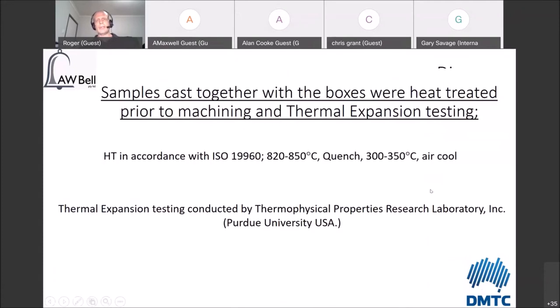So samples that were cast together with the boxes that I showed you before were heat treated prior to machining and thermal expansion testing. The heat treatment was done in accordance with the ISO standard. The specification here is just straight out of the ISO standard. We chose parameters inside of that, and it's pretty straightforward what you need to do. There's nothing special about it. And then thermal expansion testing we had done by the Thermophysical Properties Research Laboratory at Purdue University in the States. They're extremely well set up for doing thermal expansion testing, thermal conductivity testing, a whole range of things. Basically all we had to do is machine our samples, and our machine shop did a great job in producing the samples for me, and we sent them off and had them tested.